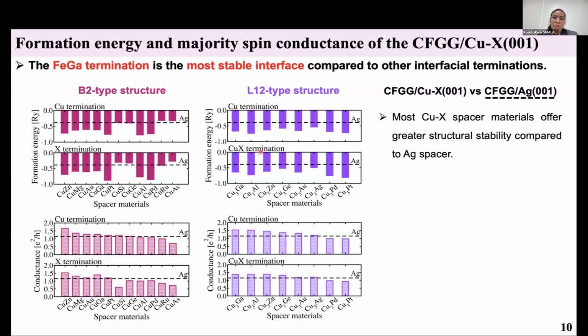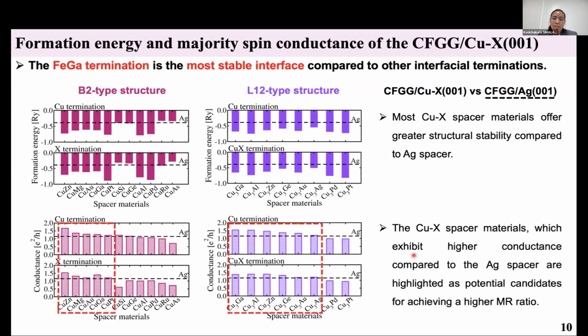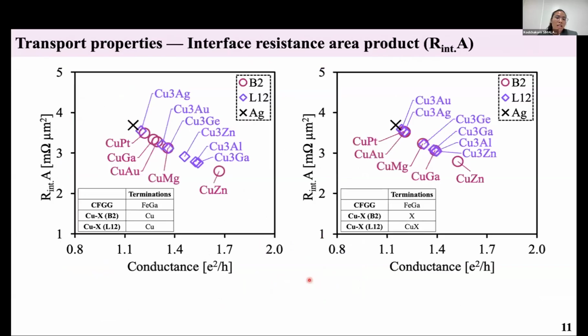So by the overall trend, the copper X spacer material provides a greater structural stability compared to when we use the Ag spacer. For the conductance, the copper X spacer materials that provide a higher conductance compared to the Ag spacer are highlighted as potential candidates for achieving a higher MR ratio, as indicated by the red rectangle here. Then the interface resistance area product as a function of conductance was investigated with the potential spacer materials highlighted from the previous slide.